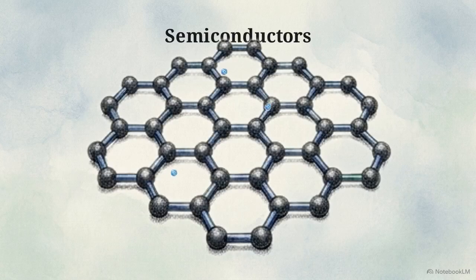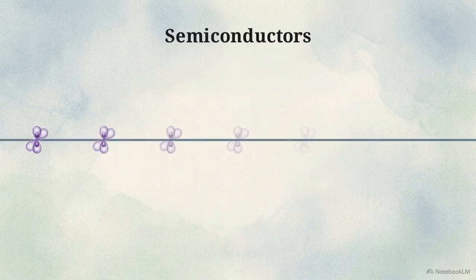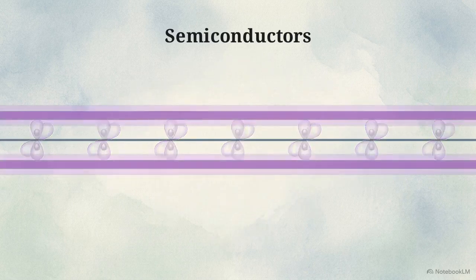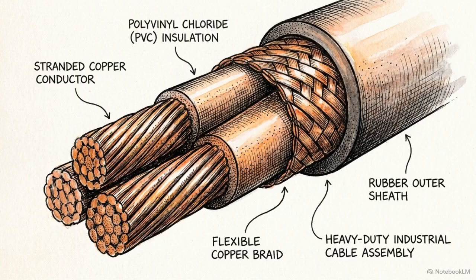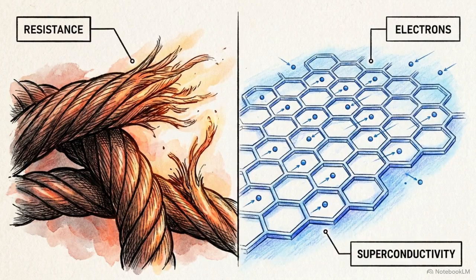Because of this linear intersection, electrons travel through the plane as Dirac fermions, massless particles that are not subjected to the effective mass that slows down charge carriers in traditional 3D materials. These particles move through the lattice at roughly 1 million meters per second, a measurable fraction of light speed. In macroscopic terms, this translates to a carrier mobility exceeding 200,000 square centimeters per volt second. At room temperature, electricity flows through graphene with significantly less resistance than it does through copper.